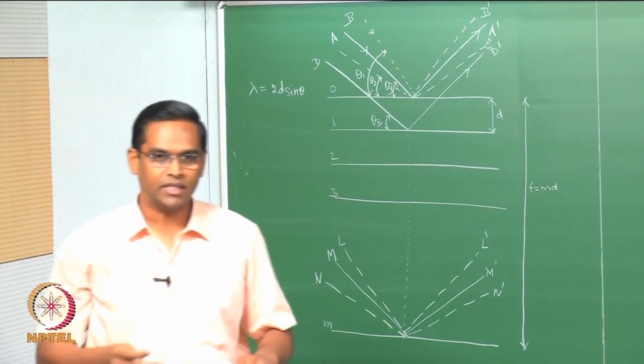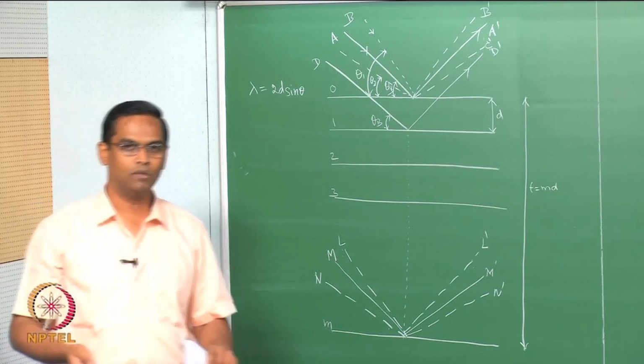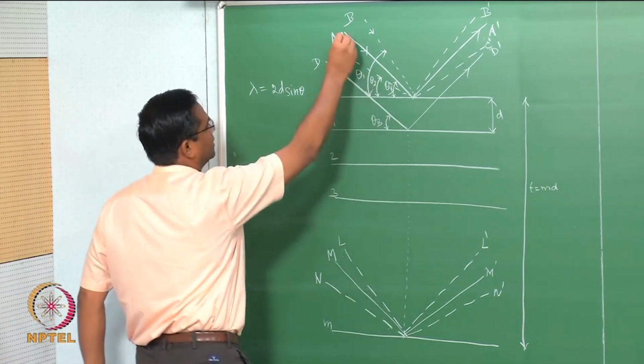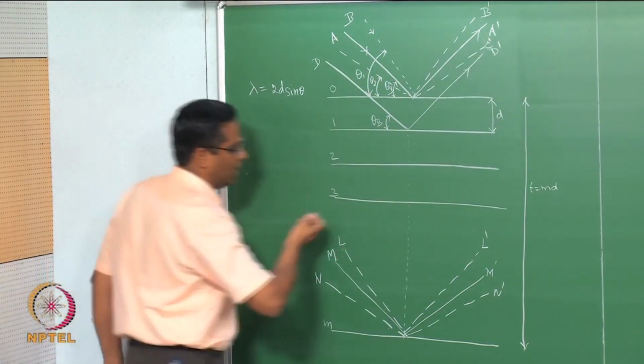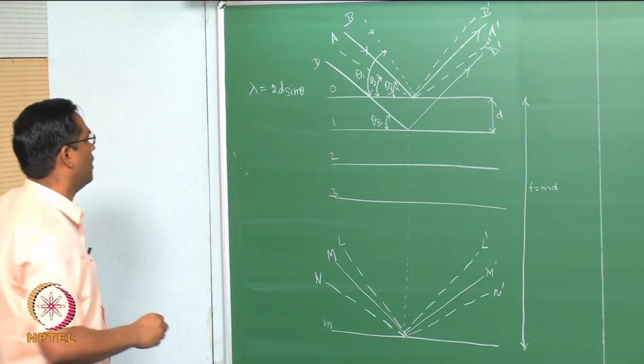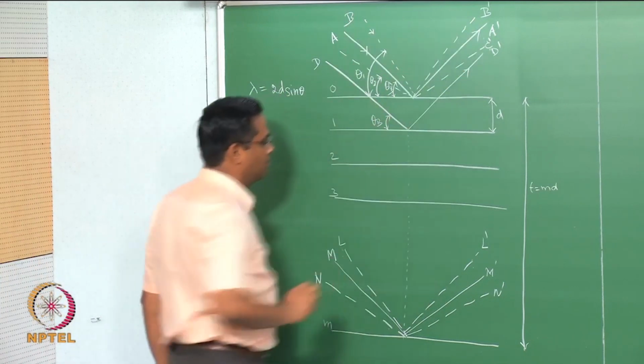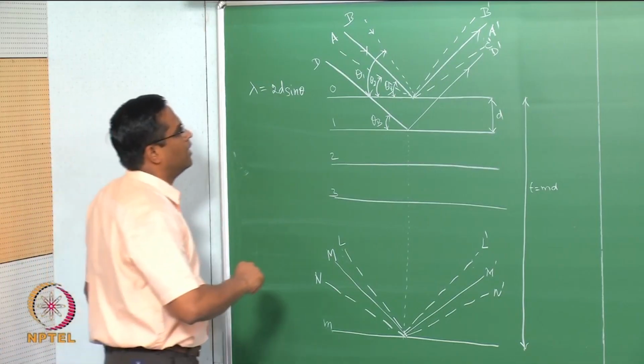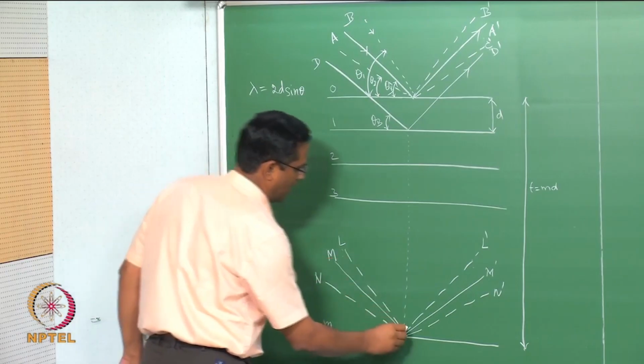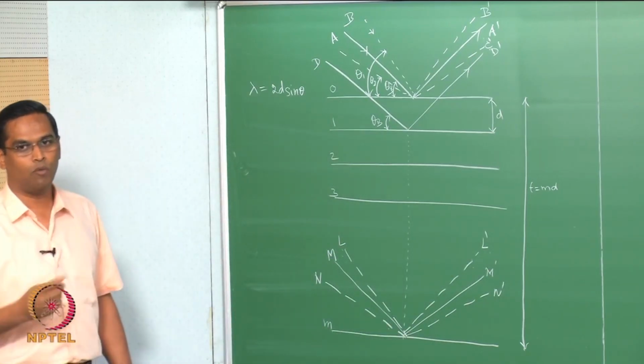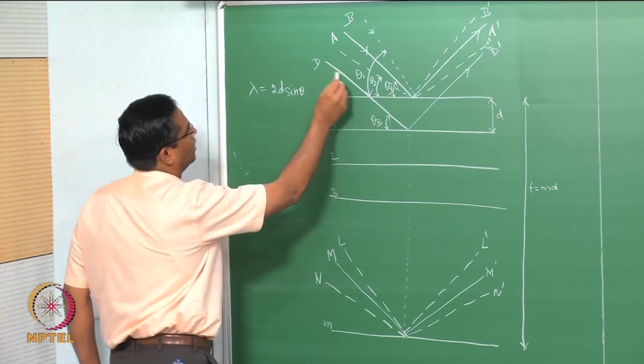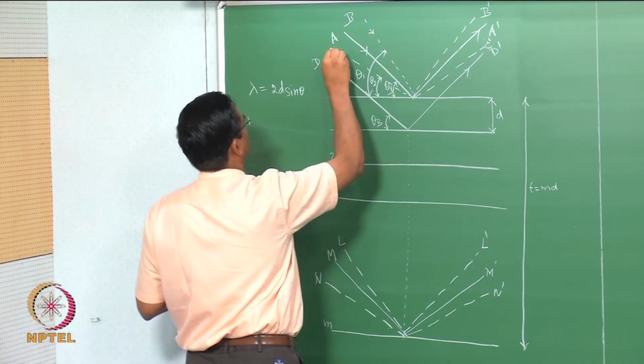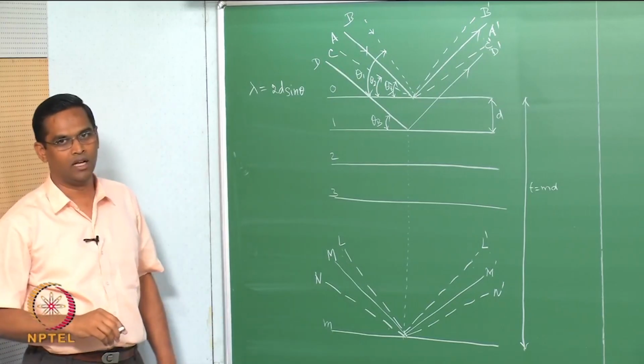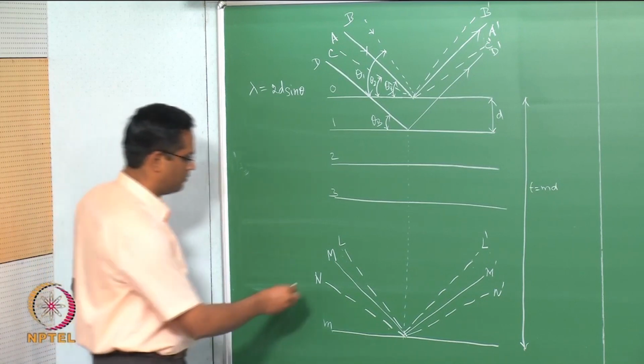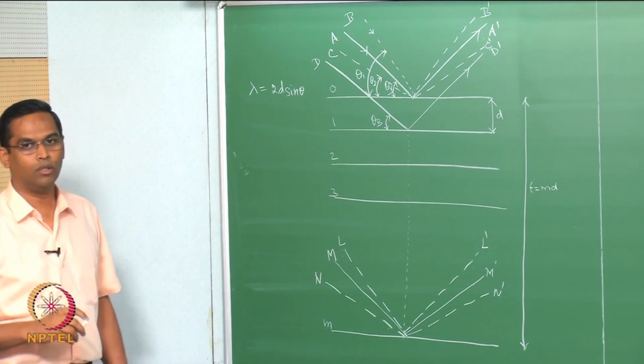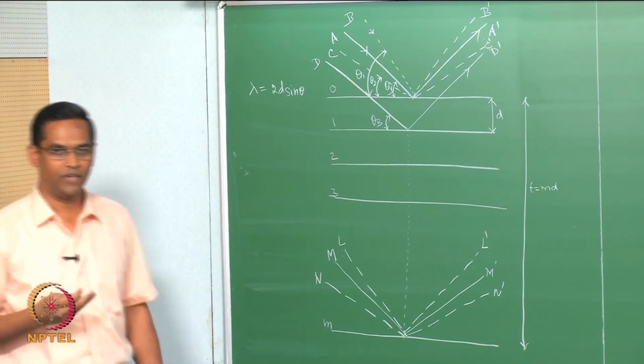Only the atoms scattered from the plane which has at least half the wavelength will cancel the scattered beam from this A prime. So, that plane will be somewhere lying in between, we do not know. But if you talk about this beam B and B prime, it will have a phase difference between L and L prime of m plus 1 wavelength, and similarly C and C prime will have a phase difference of m minus 1 wavelength with respect to n and n prime. So, these are the wavelengths at which the diffraction intensity will be 0.